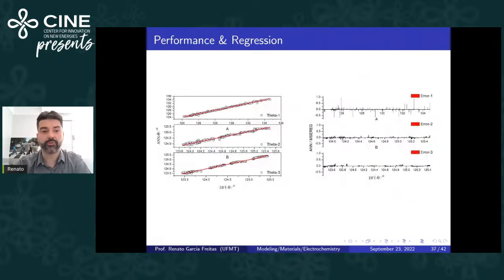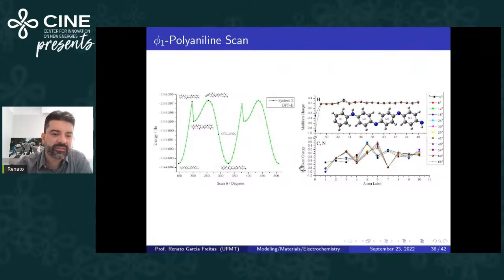0.9994. It's really good. From the DFT theta and the artificial neural network, we have theta 1, 2, 3, all of them pretty good, 0.9991 statistical correlation, and ANN mean square error, all of them lower than 1 for error 1, 2, and error 3. And we see that we increase up to this size, up to this scan, we have the jump of the polaron from the nitrogen to the carbon, isn't it?